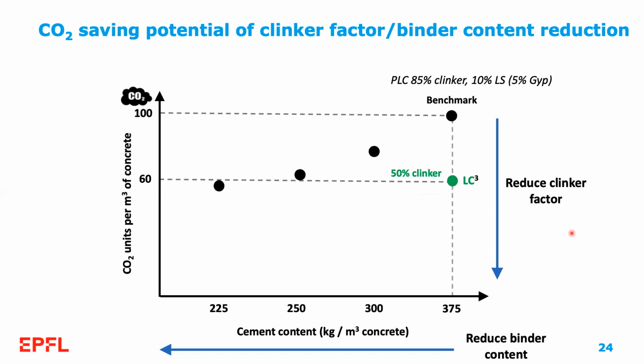If we then start working on our concrete mixture design and we reduce the binder content, we can see that we can also reduce significantly the CO2 units per cubic meter of concrete. Of course, doing the two things at the same time leads to the best reduction in CO2 per cubic meter of concrete. But I want to emphasize here that the two strategies, reducing the clinker factor and reducing the binder content per cubic meter of concrete, have similar potential to reduce the CO2 of our construction material at the end. So we really need to tackle both in order to have the best results.